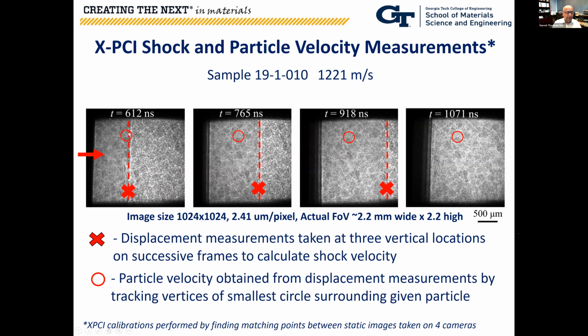We also were able to identify the particle velocity by, if you see the circle drawn around that particle, mapping the smallest diameter circle that confines a particle and monitoring the location of the vertices of that circle. The displacement of the vertices at different times gives us the particle velocity. So that way, we are now able to go inside the material and monitor the shock and particle velocity.